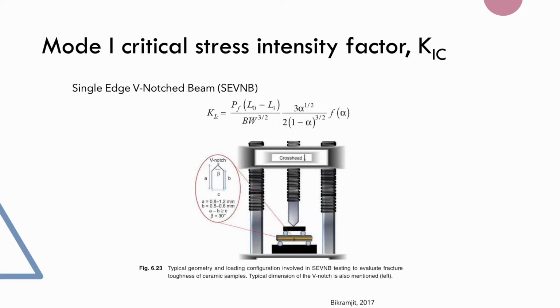On the other hand, the single-edge V-notched beam technique is a modified version of the SENB technique. A sharp V-notch is produced by polishing the notch root with a razor blade coated with diamond paste. The notch radius can be made smaller than 10 micrometers by polishing. The samples are fractured using a 4-point bending setup on a universal testing machine.